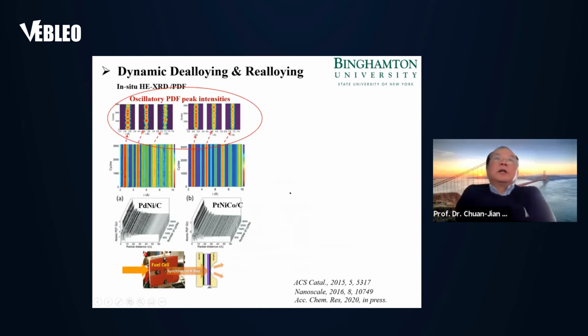Now let's show the in situ operando data. Okay, operando data. This is a set of data. We put the catalyst in the fuel cell as illustrated in the bottom. Then we measure the diffraction as a function of time. Then we process data and look at the intensity change. I want to draw your attention to the circular area where the intensity oscillates. Okay, the PDF peak oscillates, indicating the metal-metal bond distance actually oscillates during this electrocatalytic reaction.